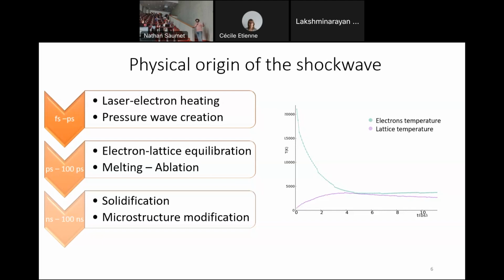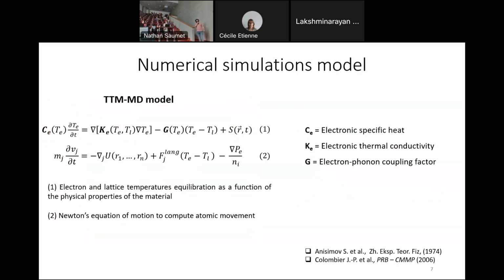There is melting and ablation which occurs, and then resolidification with microstructure modifications compared to the origin of the metal. So in order to model this peening, we need for sure a model which includes the motion of the atoms and the disequilibrium between the electronic and lattice temperature.